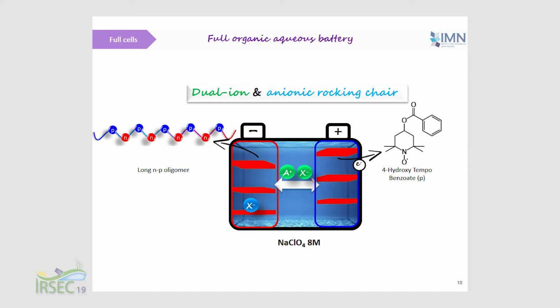So we have coupled the two materials, the long oligomer, which is N and P type, with this TEMPO molecular crystallized material, which is of P type. So of course we have a special reaction mechanism, which is both dual ion and anionic rocking chair. Of course, because you can see that we transport anions from one electrode to the other one, so this is called anionic rocking chair mechanism. But also we consume anions and cations from the electrolyte during the charge, and they are reversibly released during the discharge. So this is called dual ion mechanism. So quite special mechanism, it's quite original.